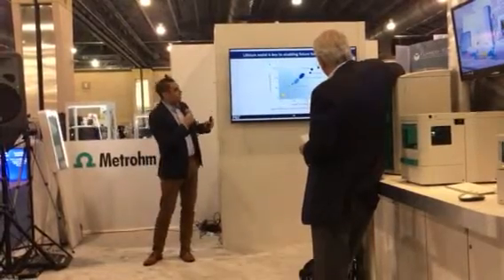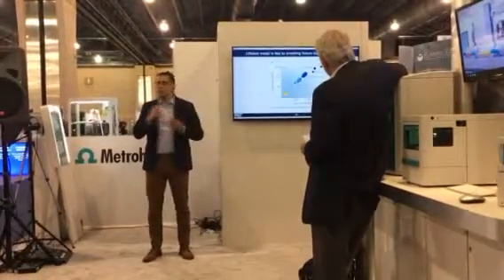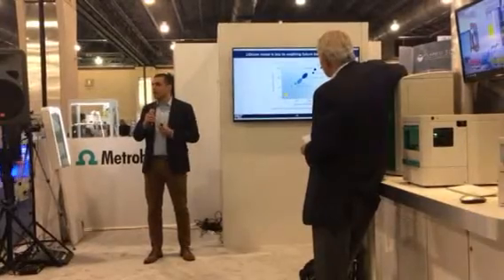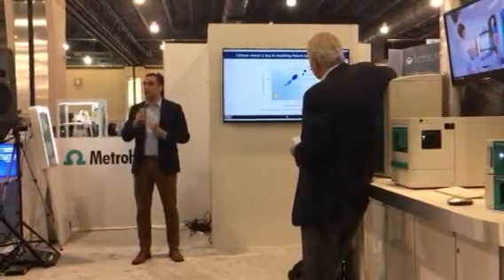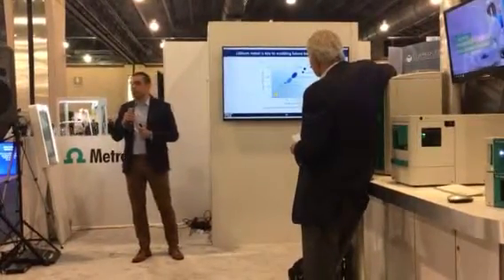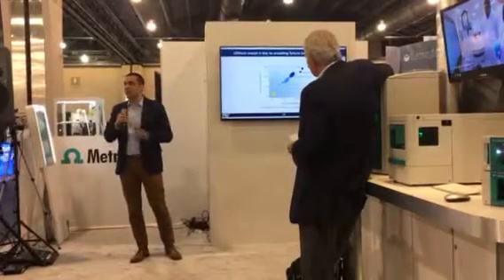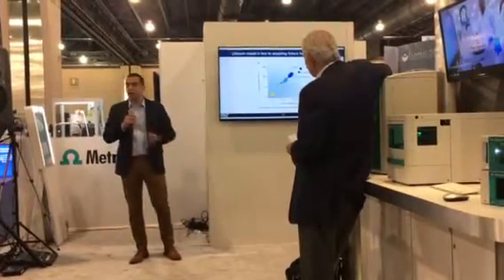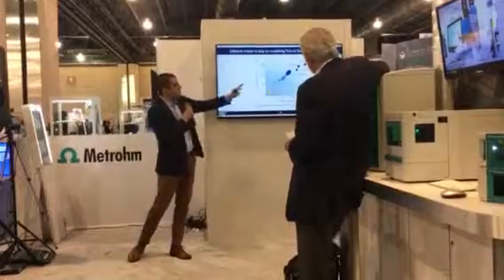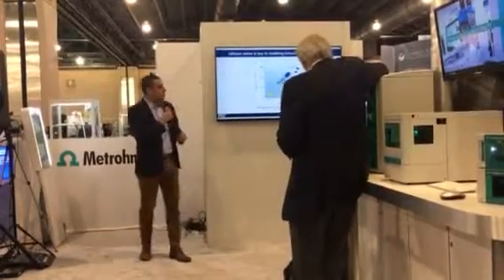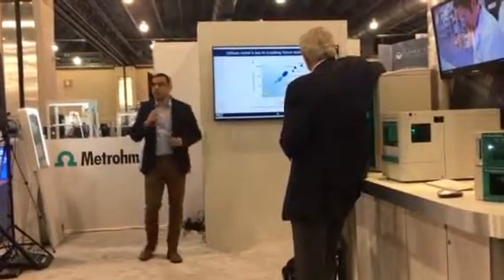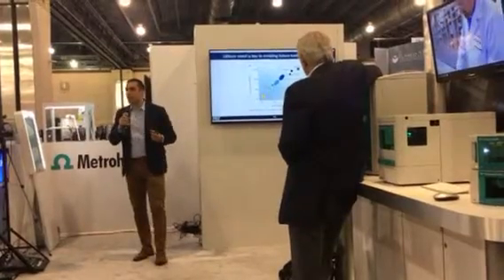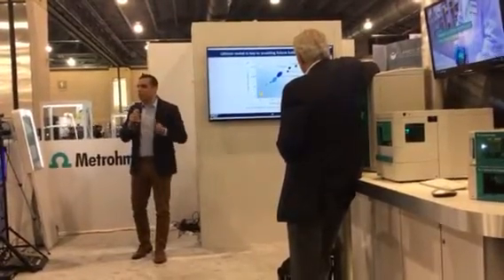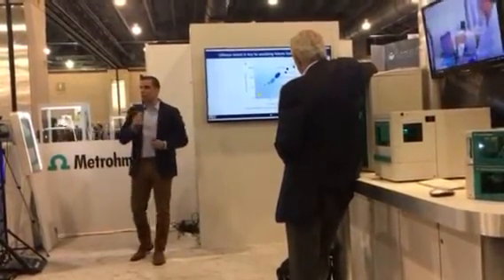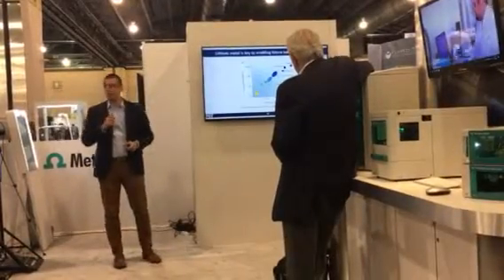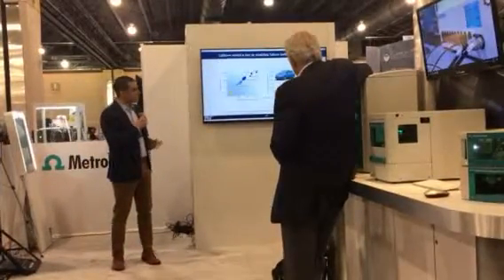And to do that, you really have to stabilize this material because it's so high energy density, it's very volatile, very reactive, and so it's actually quite dangerous right now to use. And it's the basis for all these fires that you see going on in all these different battery technologies. And when we do successfully enable lithium metal, you see it actually approaches the energy density of gasoline. So we can have an electrochemical storage technology that is almost on par with chemical fuels, which is really a game changer for these sorts of materials.